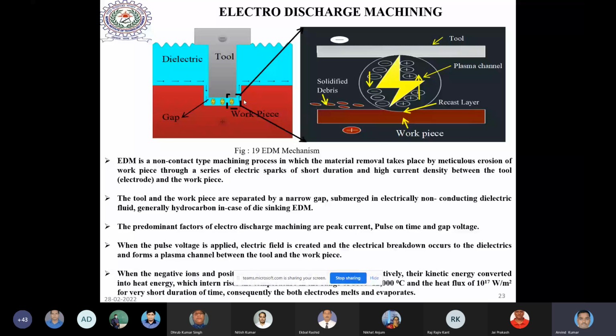Generally, we go for the tool as negatively charged and the workpiece as positively charged. The reason is that the electrons, being discharged, have less weight compared to the positively charged ions. So this is the reason we use the workpiece as positively charged, because we have to remove the material from the workpiece. More material will be removed from the workpiece if you make the tool negatively charged. Again, in this process both the materials, tool and workpiece, get eroded, and compared to the tool, workpiece erosion is more.